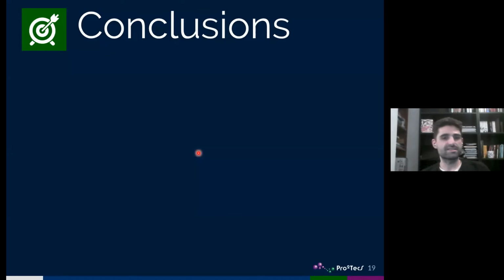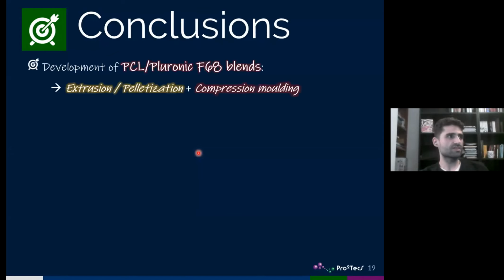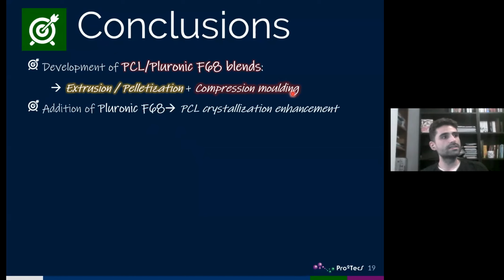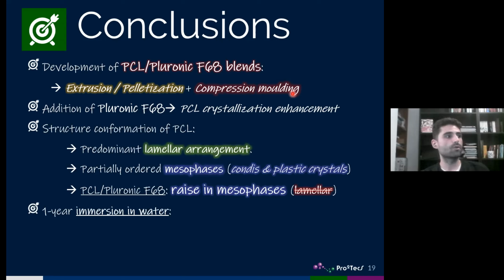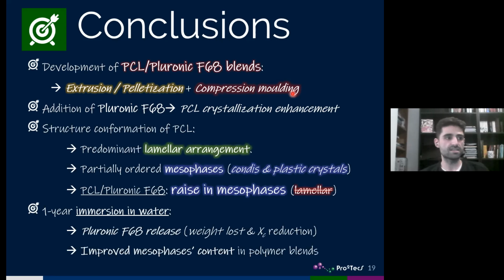Well, just to summarize the main conclusions, in this study, we modified PCL with pluronic F68 by using extrusion and pelletization, followed by compression molding processes. Then, addition of pluronic F68 promoted the crystallization of polycaprolactone. The predominant lamellar arrangement of PCL was corroborated along with the presence of partially ordered mesophases, including condis and plastic crystals. Moreover, addition of pluronic into PCL raised the mesophase content in detriment of the lamellar arrangement. And finally, after 1 year of immersion in water, we found the release of pluronic into water by both the weight loss of the samples and the reduction in the crystallinity degree, also increasing the content of mesophases after that immersion process.